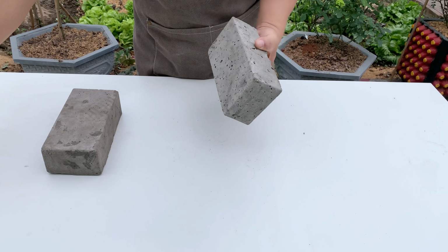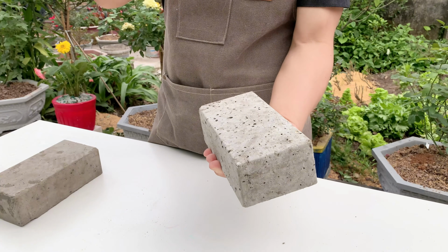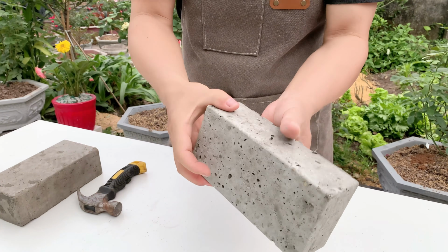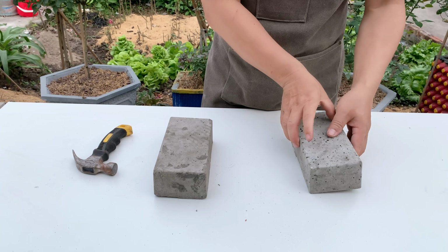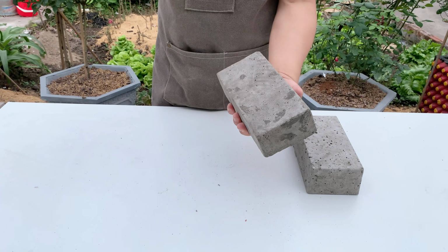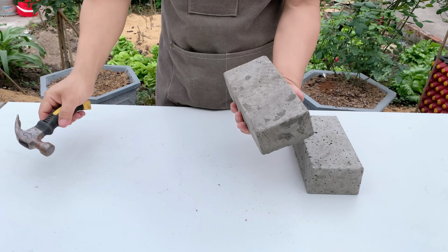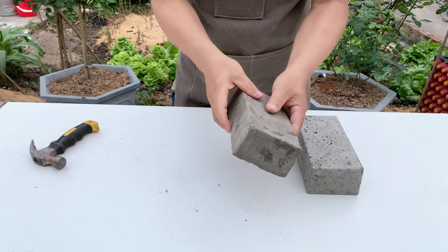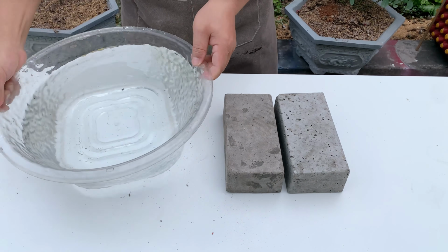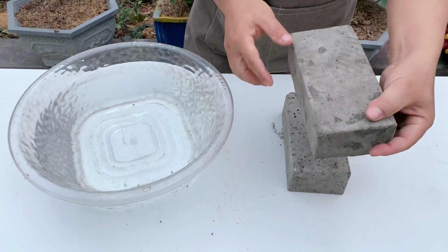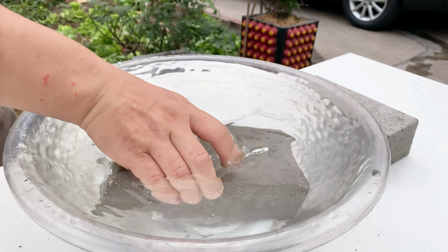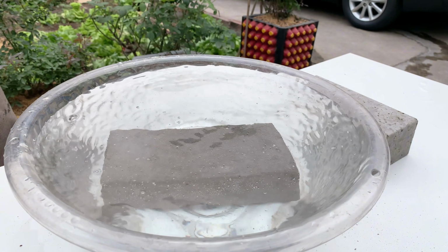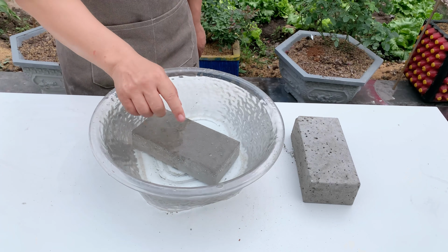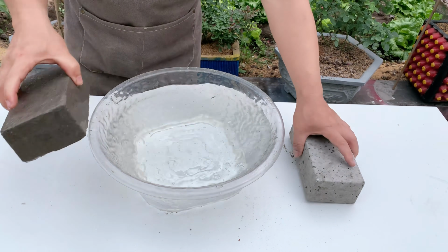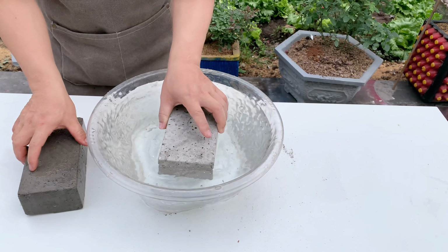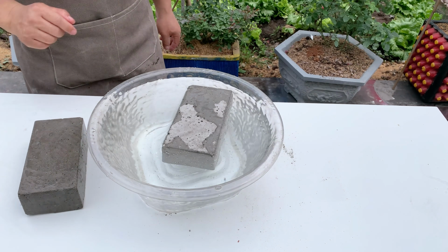So now we test that too. Using a hammer, the normal concrete block gets struck repeatedly. The surface feels hard and solid, exactly as expected. Now let's do one final experiment. Both blocks go into water. The normal concrete sinks heavily downward because of its high density. Meanwhile, the foam concrete behaves differently because of all the trapped air distributed inside the structure. And this creates some very interesting possibilities for lightweight building projects.